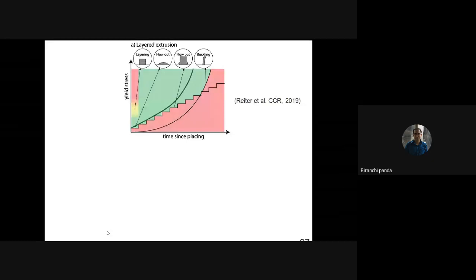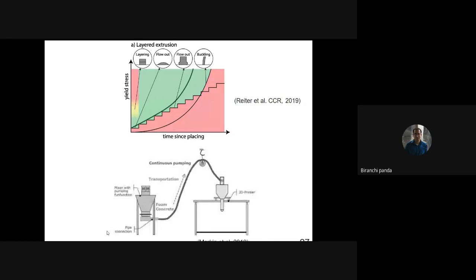So how does it happen? You can see the schematic of the 3D printing system. At the extruder, we try to add some chemicals. We call it an accelerator. They usually make some changes in the material chemistry and try to create a rapid hardening mix. Once you deposit this rapid hardening mix, you can deposit more layers. You don't have any fear of collapsing the entire structure.